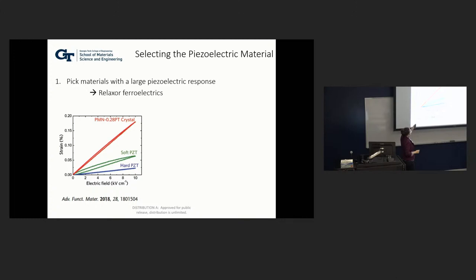These are a couple of other piezoelectric materials that you might have heard of, and this relaxor, which I'll talk more about the composition in a second, actually does significantly better. It's again in this perovskite crystal structure, where lead is on your corners, oxygen is at all of your face centers, and literally everything else is at the center B-site cation. They just threw the kitchen sink at these things until they found what was optimized.